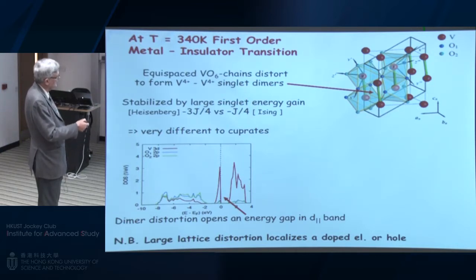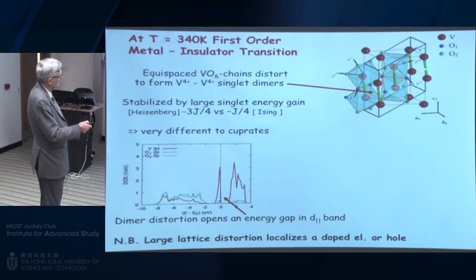Instead, this nice linear arrangement of vanadiums turns into a set of dimers. These move together to form dimers. And again, it's this 3J/4 that I mentioned earlier, this singlet binding energy, which is doing now something different. It's forming pairs, because now we only had a line of vanadium atoms, whereas in the other case we had a square lattice of coppers. So now it just gains this singlet energy by distorting it, forming a lattice of dimers, and that can open